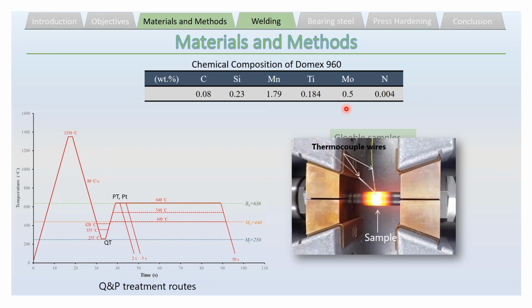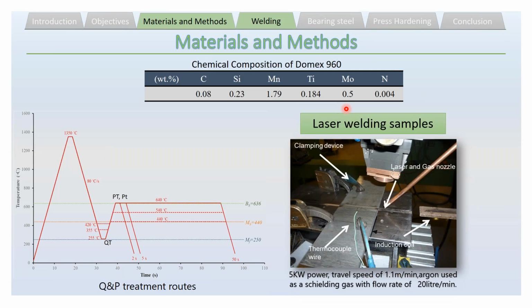So 27 different conditions. All the samples were treated in Gleeble, and based on the microstructure and the hardness results, we selected a few of them to test by real laser welding, using an induction heater to apply the heat after quenching, so in the partitioning stage. During this time, 2 thermocouples were welded 1.5 millimeters from the fusion zone to control the temperature, because the most critical area for the failure of the welds is the coarse grain heat affected zone. So we want to control that area and have the best results there.